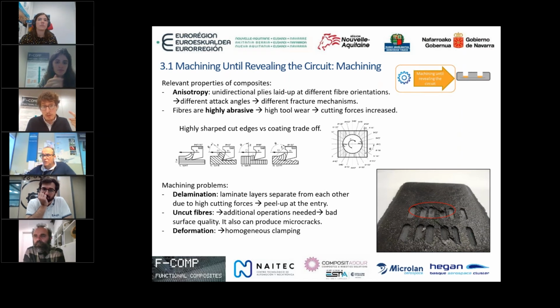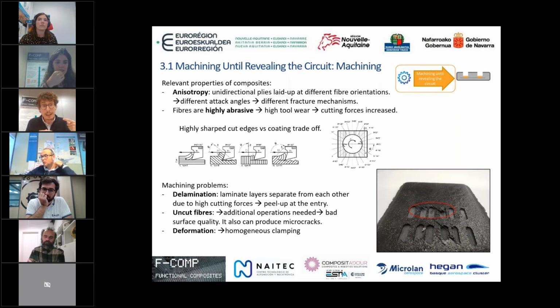For solving the issue of the anisotropy, we need very sharp cutting tools. But on the other hand, for solving the highly abrasive problem, we need to put some coatings on top of the cutting edge that reduce this sharpening of the edge. So it is needed to do a balance of these 2 things. The problems that MICROLAN has found in the machining, you can see in the image bottom right, there are different trajectories or different ways of trying to do the same machining.